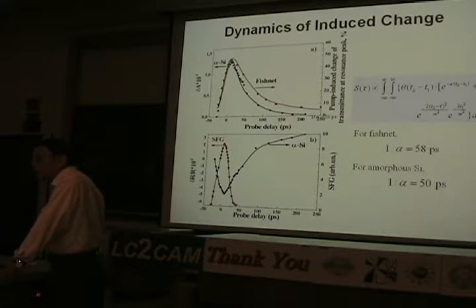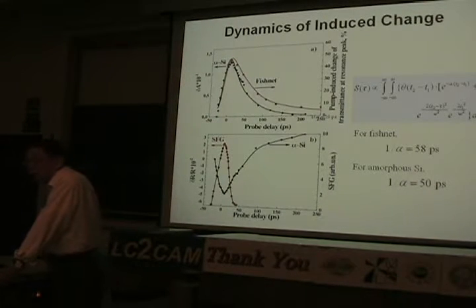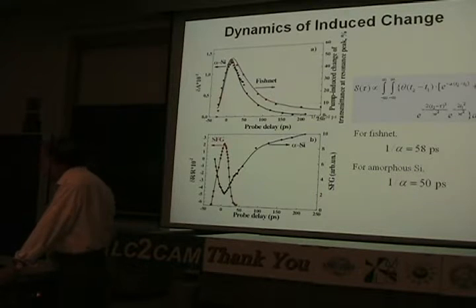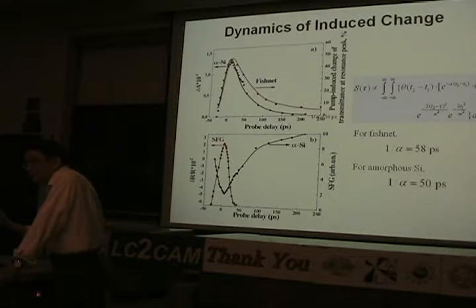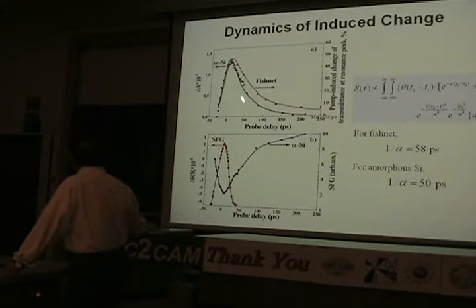Now, actually, we recently made the femtosecond measurements and found this response time, or the relaxation time, can be even shorter. Because here we use a 20 picosecond laser pulse to do the experiment, what we found is this kind of relaxation time scale is of the order of tens of picoseconds. And now with femtosecond, 100 femtosecond pulses, we actually saw a 1 picosecond peak relaxation, which of course cannot be seen here because it's sort of integrated out. And so we're still trying to figure out whether this very, very fast modulation can be effective in changing the transmission.